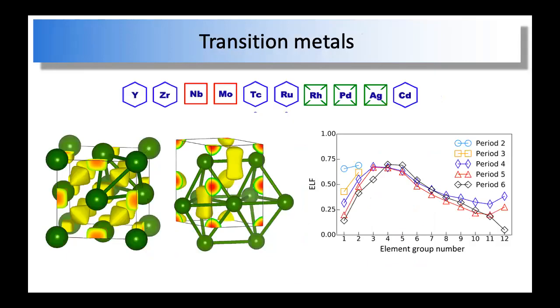For transition metals, you see a similar feature. Forget about the body center. Let's just compare the HCP and FCC structures. Then we can see that for early transition metals, you have a large occupation at the tetrahedral site. Therefore, you have a stronger bond between these two quasi-atoms, and therefore it stabilizes the HCP structure. And the general trend is that the electron localization becomes lower and lower for both octahedral and tetrahedral sites, right?